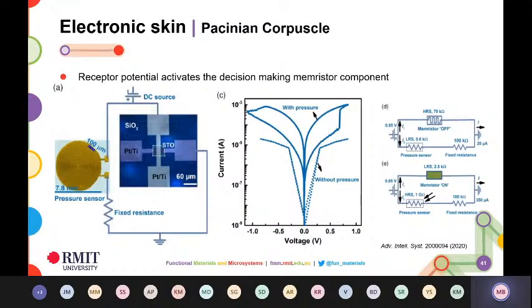So the first thing which we demonstrated was a Pacinian corpuscle. Now this is the biological term, but essentially what it does is measure pressure. If you look at all your fingers, you'll actually see the most obvious Pacinian corpuscle, which you can see on your skin. It's essentially sensing for pressure all the time. So having a pressure sensor connected up to brain mimicking electronics, having the strontium titanate based memristor sitting along with it, allowed us to mimic this pressure sensing aspect of it. It's extremely electronically driven. The high resistance states or the low resistance states of the pressure sensor, depending on whether it's seeing pressure or not seeing pressure, drives the memristor between those two states, and that decides the responses that the body generates.